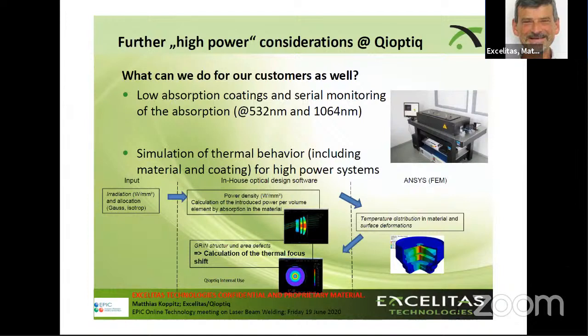And so a very good low absorption coating is necessary. We develop such a coating, but we do not only say it's low absorption. We have an absorption measurement tool in-house to monitor our serial production. Each low absorption coating batch is monitored and tested with this tool. And this is not only for 1064 or 1070 nanometers; we are doing this for our low absorption coating for green, for 532 nanometer.